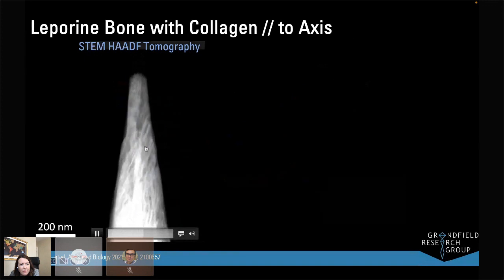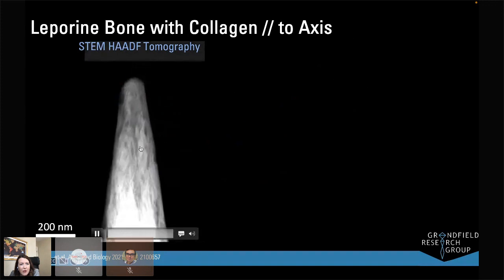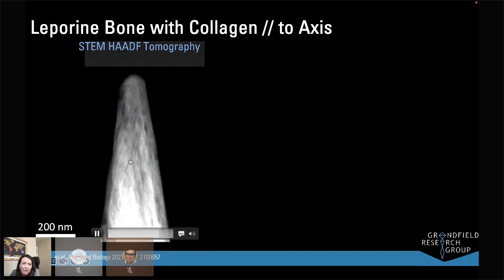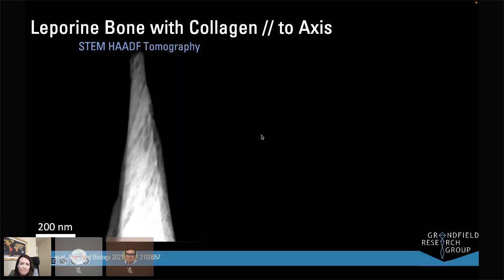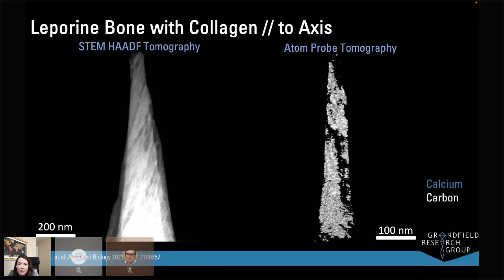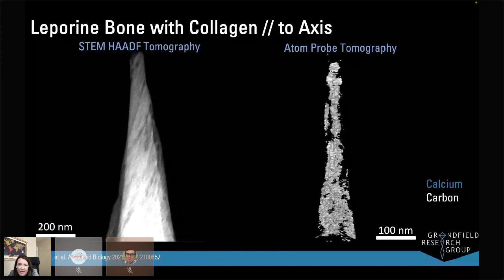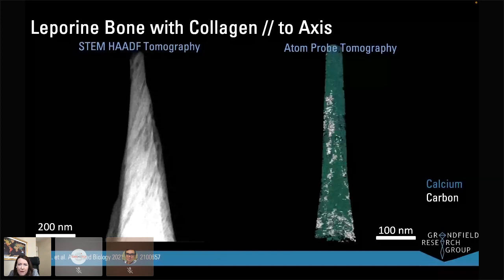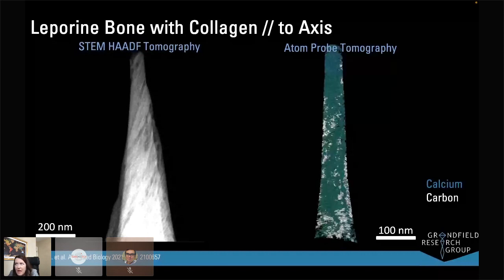We see our collagen fibrils and hydroxyapatite fibrils are aligned roughly along the length of the atom probe needle. Then we perform atom probe tomography on this sample where we know ahead of time the orientation. What we can see here is this 3D data set where we have carbon, our collagen-rich phase shown in silver, and calcium, our hydroxyapatite mineral shown in teal. We can explore this in 3D.